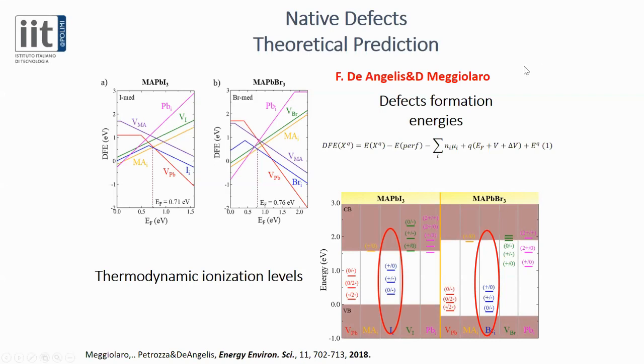So what we know from these studies is that the large density of defects belong to vacancies, mainly of the cation, that is the organic cation, which is in the middle of your cage, which generally is a methylammonium or cesium cation. But there is a density which is low but is not zero of halide interstitials, which actually introduce, as I'm showing here, defect trap states within the band gap.